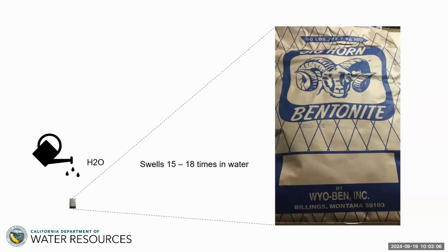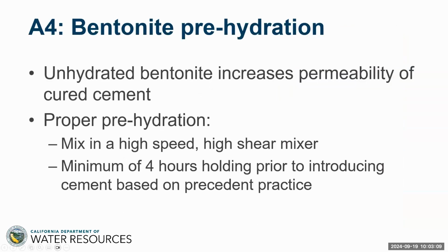Now, if you go to the next slide, then, if you use unhydrated bentonite, i.e. you just throw some dry bentonite powder into a grout mix, it can increase the permeability of cured cement. So this is a negative thing. And in fact, just adding bentonite powder to an already cement-water mix is absolutely a waste of the beneficial properties of bentonite, because the cement-water reaction, as you know, is very alkaline, and that will inhibit the ability of the bentonite particles to expand and contribute. So you might as well just put in non-reactive clay. It would be a lot cheaper than unhydrated bentonite.